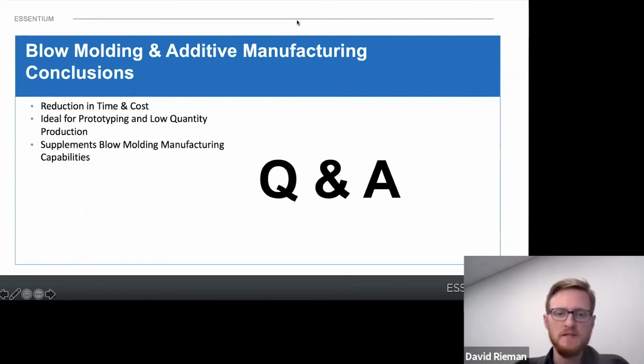How many cycles can a 3D printed mold withstand on average, and what's the cycle time? I think that I mentioned earlier that for a traditional extrusion blow molded part, a larger part might have a cycle time of about 60 seconds in the mold, and the 3D printing cycle time would probably be in the 80 to 90 second range. But again, you can't run them back to back like you would with a traditional metal mold, because there are no coolant lines, and because of that poor heat transfer, you have to basically let the part air cool, or blow cold air over that part. I don't have information on how many cycles they can withstand.